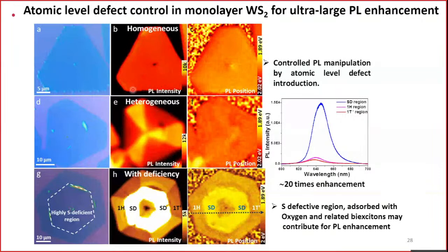Interestingly, compared to the other regions I mentioned earlier, the 1H region and the 1T region, that variation we know. But if you look only at the center region where the sulfur is severely defective, there we saw almost 20 times enhancement in the photoluminescence, which means that after the sulfur is stripped off, close to one layer at least, more and more absorption of oxygen is possible. As I said earlier, whenever we have oxygen absorption, they essentially can induce a lot of biexcitons. That is what probably